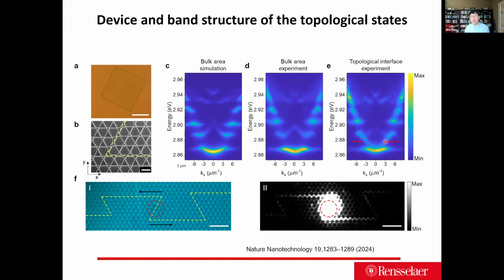So eventually, the system chooses by the material's gain spectrum. Essentially, the photoluminescence has a quantum yield where certain areas of the gain spectrum like to condensate more. So essentially, you have a gain-loss system. Your gain at certain spectral region always wants to condensate first. So we can do the patterning. We know that the region that always wants to condensate is in the 429, 428 region. So we make the topological gap center around that.